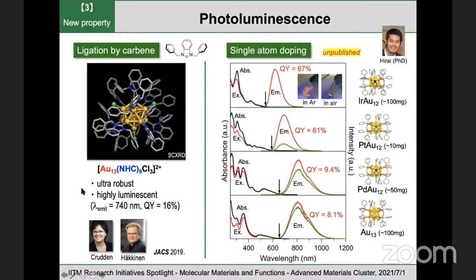And very recently, one of my PhD students discovered that the iridium doping at the central position of the icosahedral gold superatoms can enhance the photoluminescence quantum yield up to 70%. So this is very bright superatoms. Next, please.